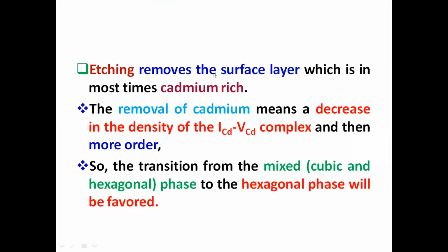Etching, as you know, removes the surface layer. In our case, it is most probably cadmium rich. The removal of this layer decreases a complex known as ICD-VCD, and removal of this complex makes the films more ordered, and then it encourages the change from mixed phase to hexagonal phase.